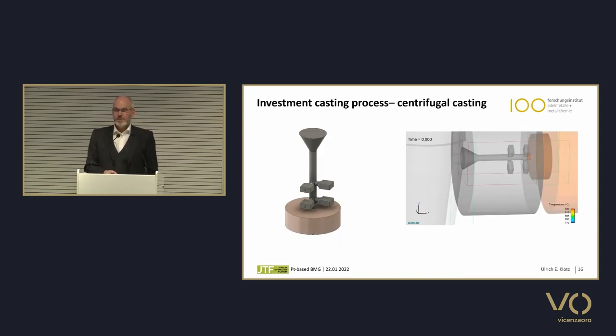Now, this is a video, so could you please play the video? So you see the melt coming up and shooting into the mold. It's done very quickly. And we saw, if you look at the time here in seconds, you see form filling is really fast, and then it takes around 2 seconds to reach temperatures where the material solidifies or becomes amorphous.